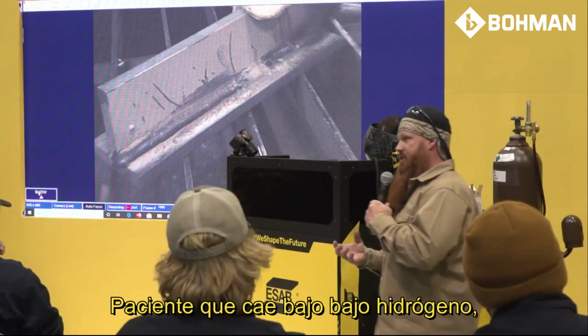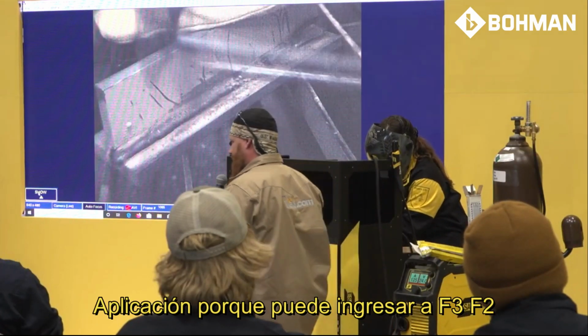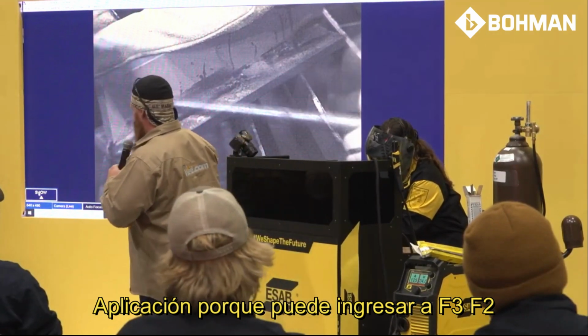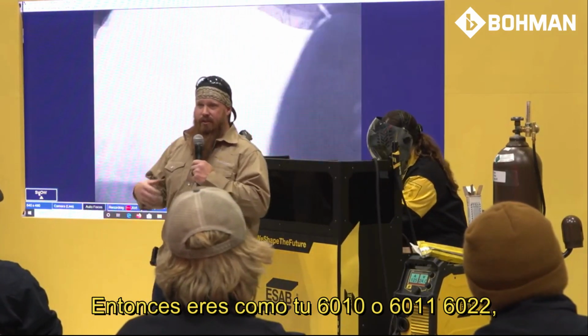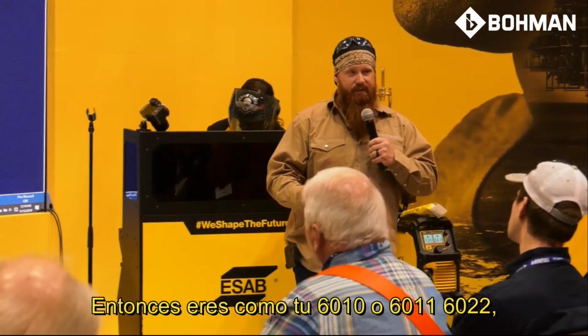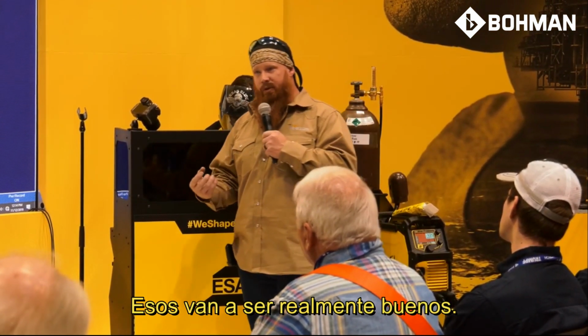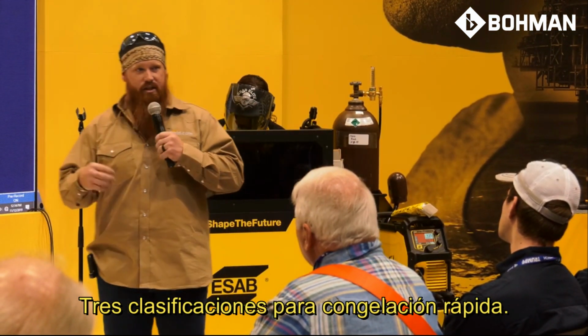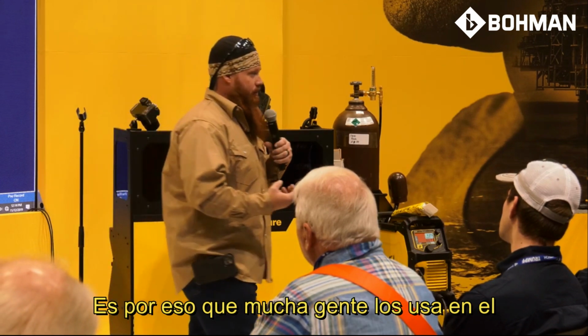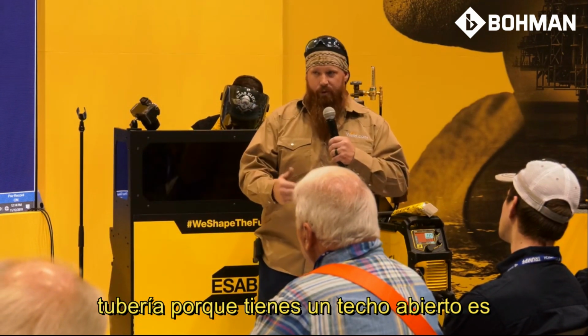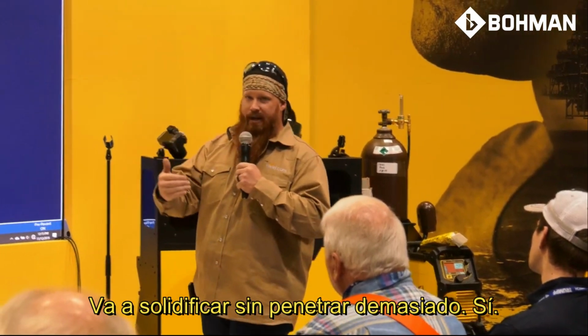That falls under low hydrogen, which makes it good for structural steel applications. But then you can get into F3, F2, and F1 classifications. So your 6010s, 6011s, 6022s, those are going to be really good. They're going to fall in the F3 classification for fast freeze. So that's why a lot of people use them on the pipeline, because you have an open root. It's going to solidify without over penetrating.